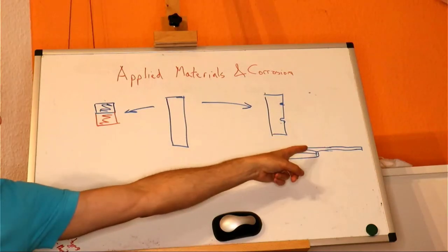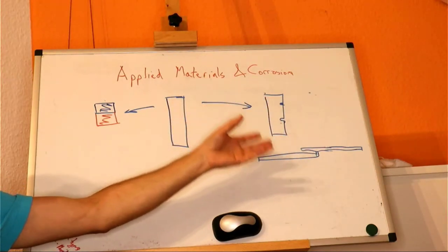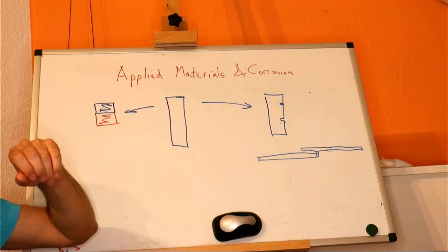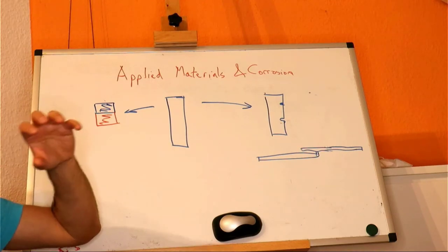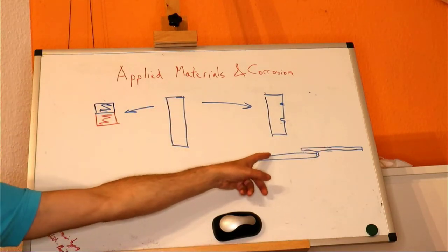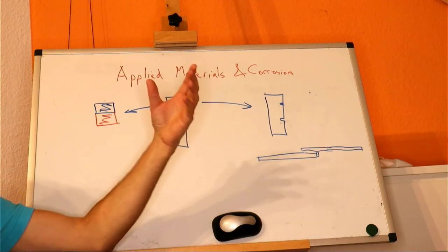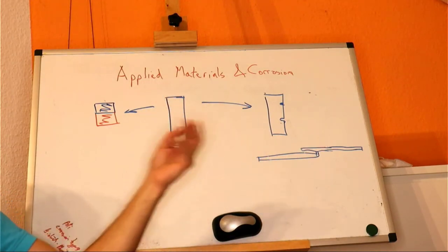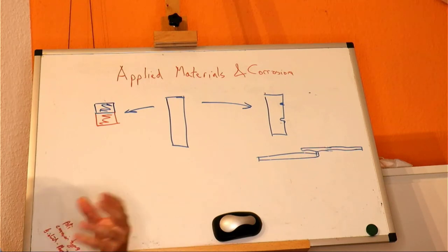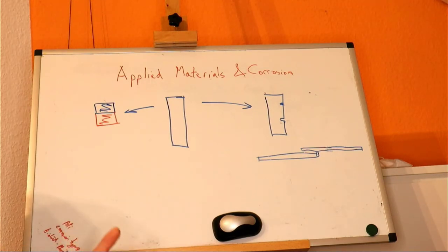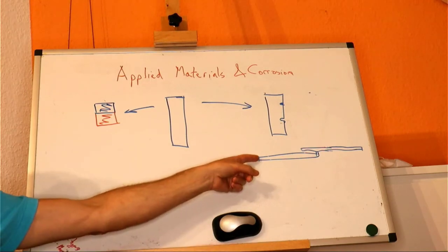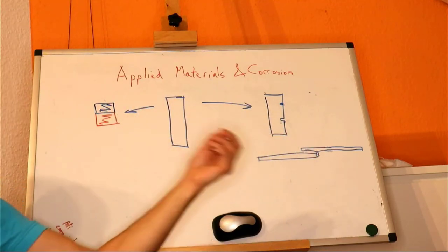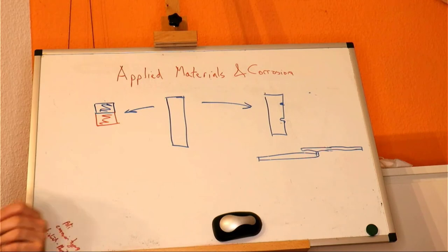If the oxygen gets used up inside the hole, that will make the area inside the hole different to the area outside. The oxygen will get used up, and so it won't be being reduced here, and the oxygen will be being reduced on the outside, but the metal can be oxidized all over. And it turns out that oxygen being reduced generates hydroxide ions, metals dissolving generates metal ions, and so we end up with metal hydroxides typically. But if we run out of the ability to make new hydroxide ions, it means that this gap can become acidic, and depending on the metal, it can then corrode faster.